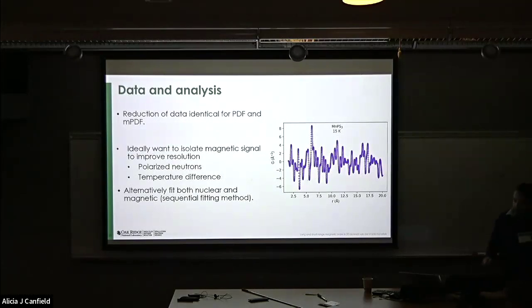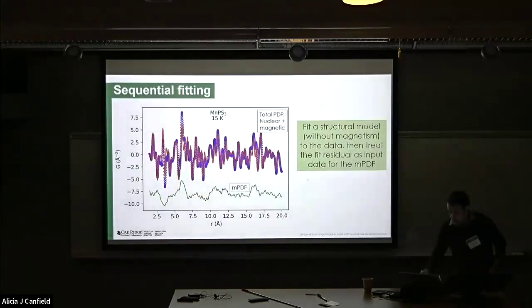So for the data analysis, there's kind of 2 ways to do it, and this dictates what resolution you get. So what I showed earlier for the red and the blue plots. If you're able to fully isolate your magnetic signal, you get improved resolution. And ways to do this would be polarized neutrons or doing some temperature difference. In practice, this can get very challenging. The alternative way is you just fit both the nuclear and the magnetic part. If you're working in reciprocal space, this is easier. You can typically isolate what is the magnetic scattering, what's the nuclear scattering. If you're looking at your PDF data, everything is kind of mixed together. So it becomes a little bit harder to do, but you can do it.